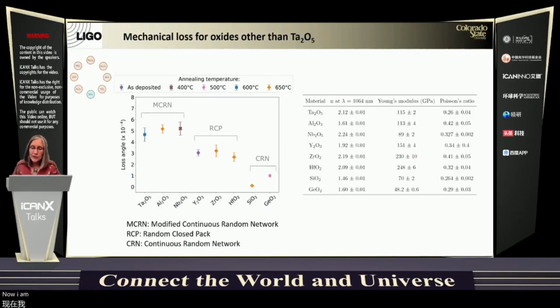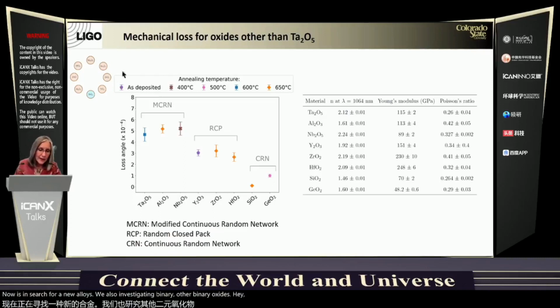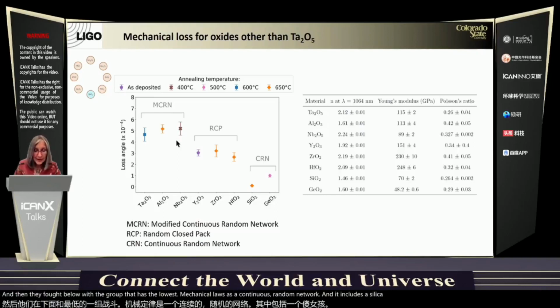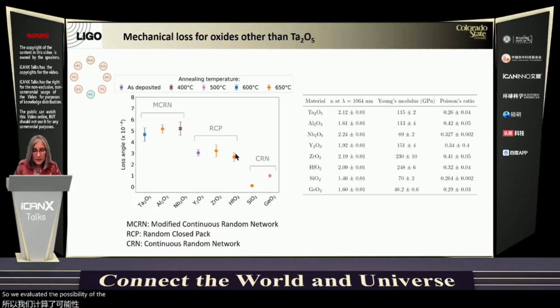Now, in search for new alloys, we also investigated other binary oxides, and here I plot the loss angle for a family of binary oxides that are arranged according to their coordination. For example, tantala falls within the group of modified continuous random network, and it has a mechanical loss of about 5×10⁻⁴. The next group includes yttria, zirconia, and hafnia, and is identified as random close pack. And then the group that has the lowest mechanical loss is the continuous random network, and it includes silica and germania. So we evaluated the possibility of designing coatings with hafnia and zirconia.